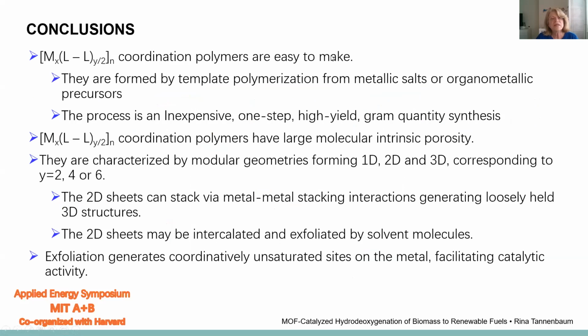So in conclusion, we see that these kinds of coordination polymers are easy to make, and they're formed by what we call template polymerization, because the ligands actually dictate the way the polymerization is going to occur. The process is inexpensive, one-step, high yield, really gram quantities or more. The coordination polymers have large molecular intrinsic porosity, which facilitates the flow of reactants and products.